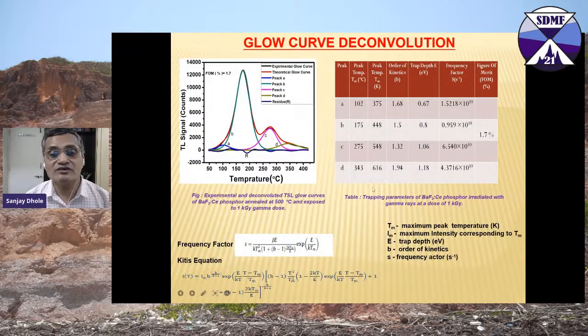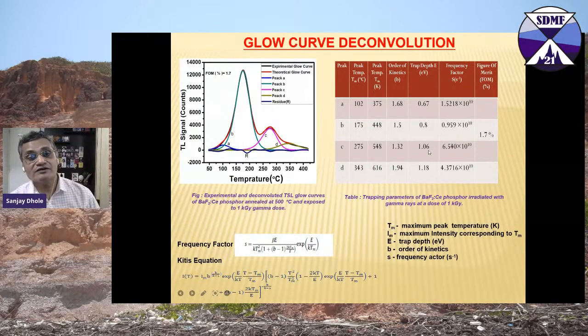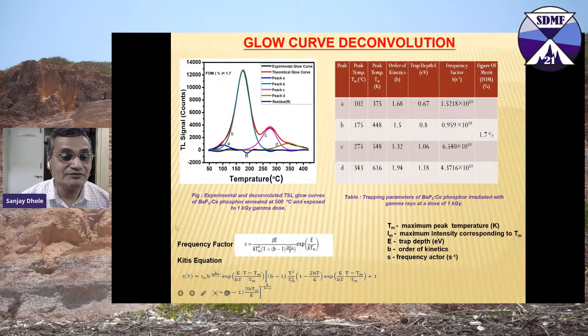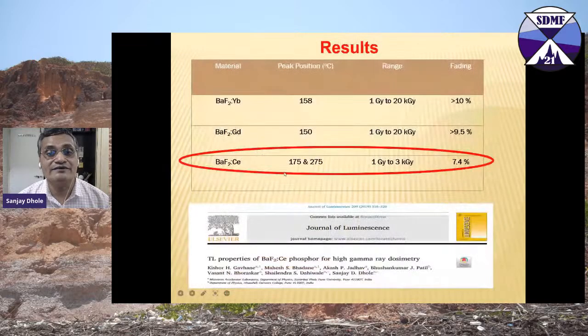This is the glow curve. We can get the maximum temperature, order of kinetics, trap depth, frequency factors, and figure of merit. The figure of merit for this is 1.7%. If the figure of merit for a nanophosphor is less than 2%, it is always good. This is the frequency factor, and this is Chen's formula, which has been used for the theoretical calculation of all these factors. And this has been deconvoluted.